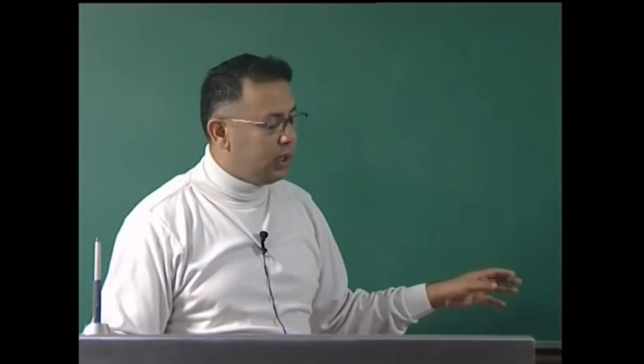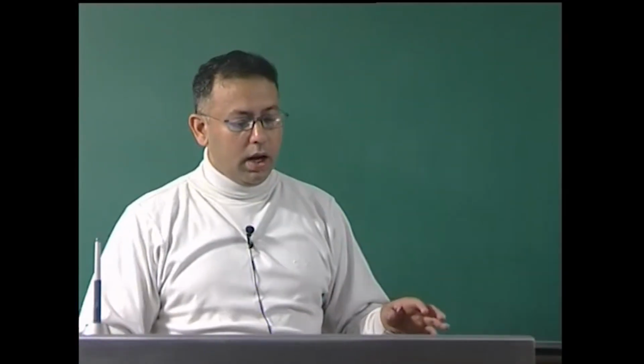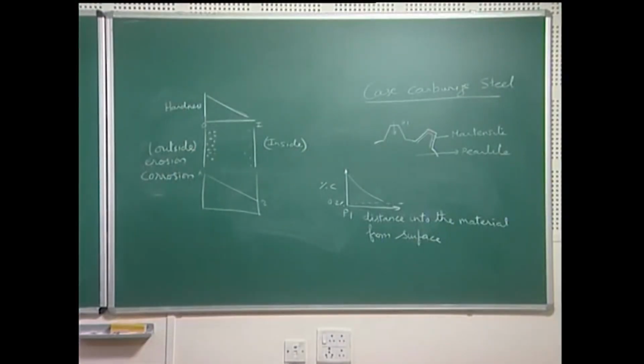Therefore, in this example you can clearly see that I have under my control the variable which is composition, I have under my control a gradation in composition, and I have under my control the formation of the kind of phases, like the phase on the surface is martensite, the phase in the interior is more like pearlite, which is actually not a phase, but a microconstituent. So, I can have a gradation in the formation of the phases and microconstituents, and therefore, I have a handle on the properties.